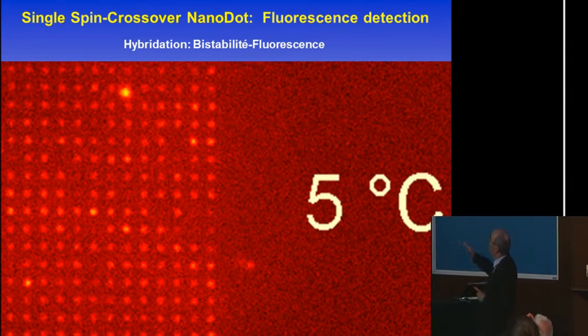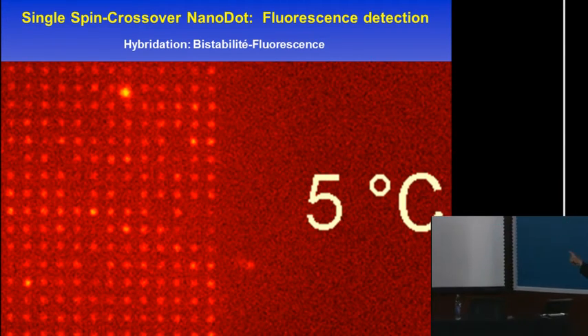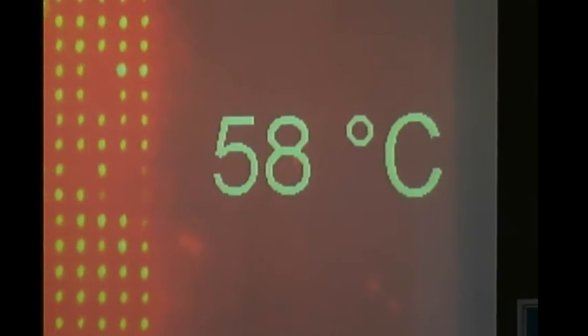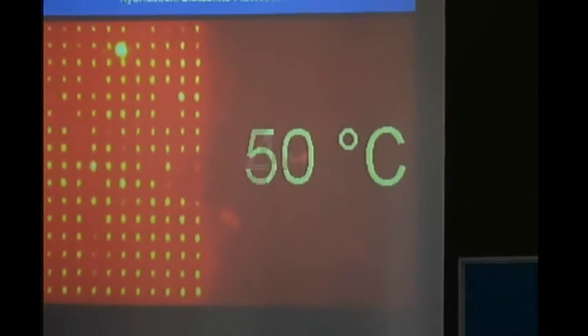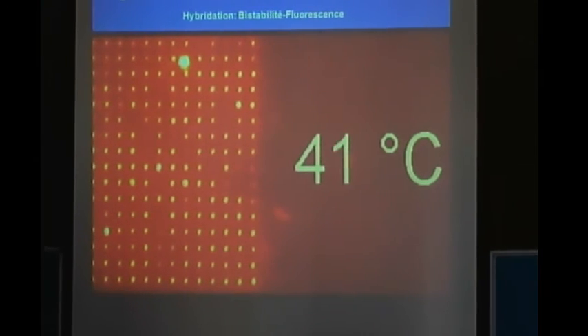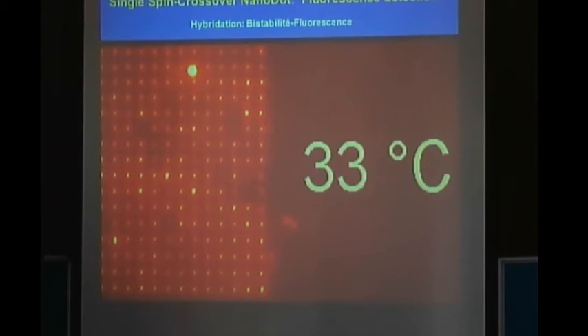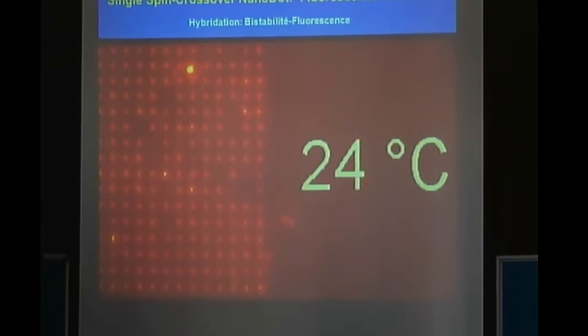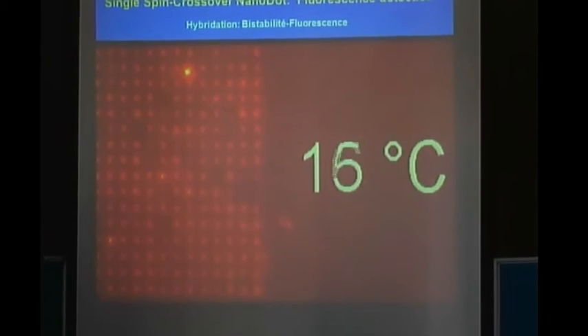Here, we are in the low spin, always low spin. The high spin is around 50 degrees. You will see, here we have the crossover. Okay? You see that light is all absorbed or it's released through the spin crossover. That means that you can make the switching by temperature of your crossover and you can quench or not your luminescence.